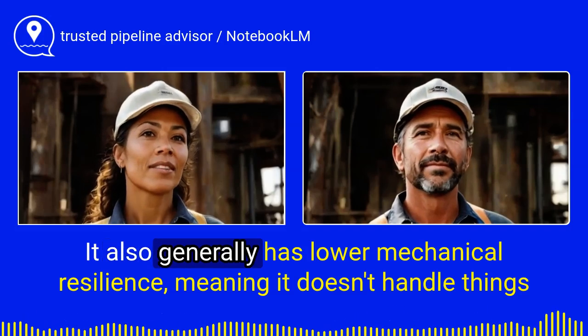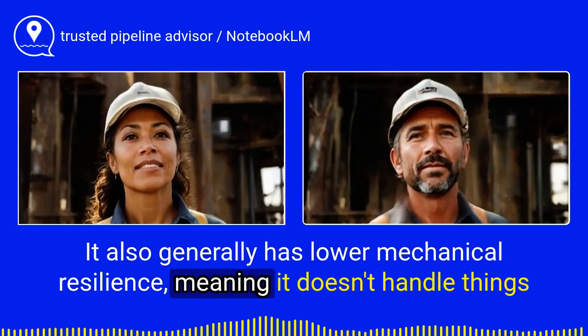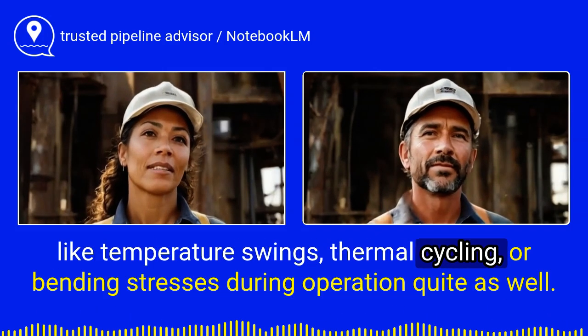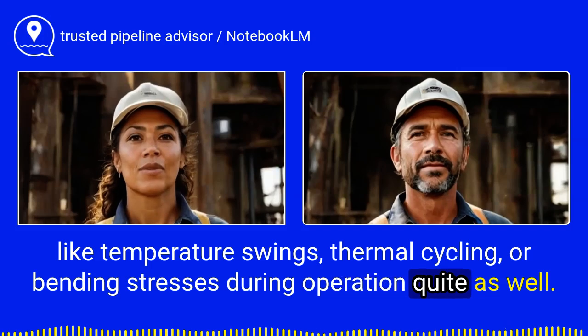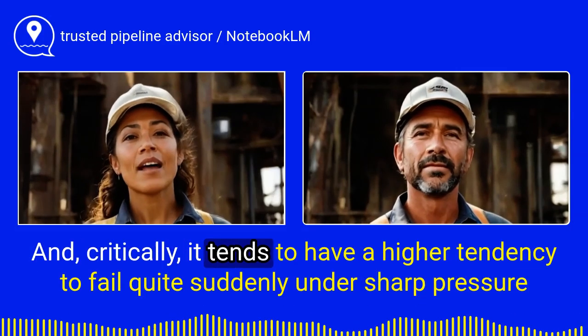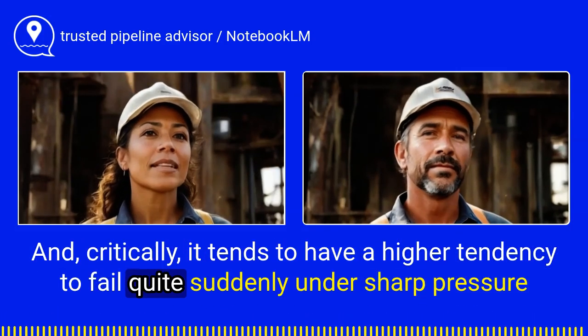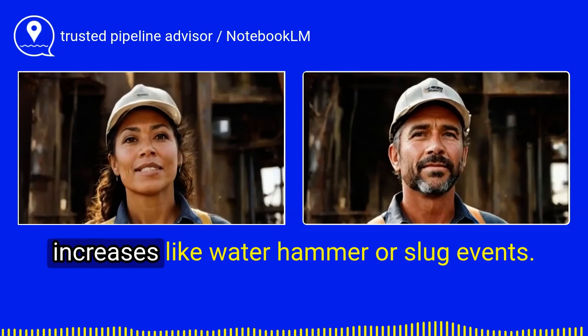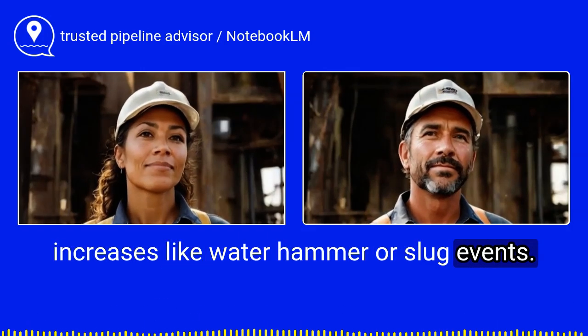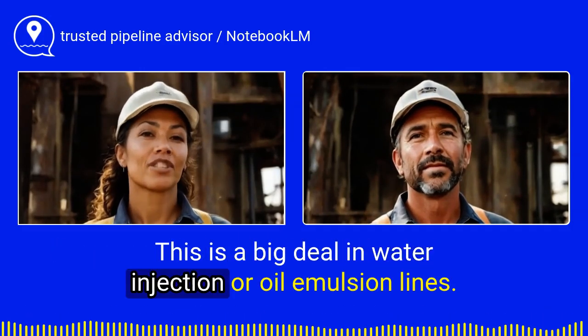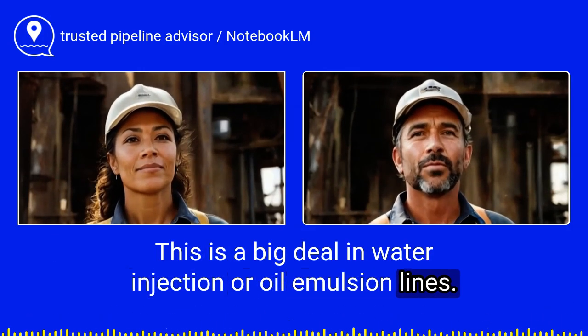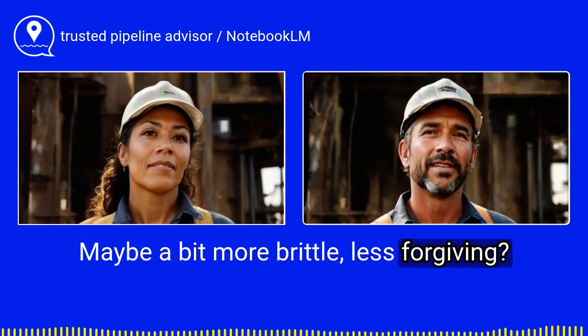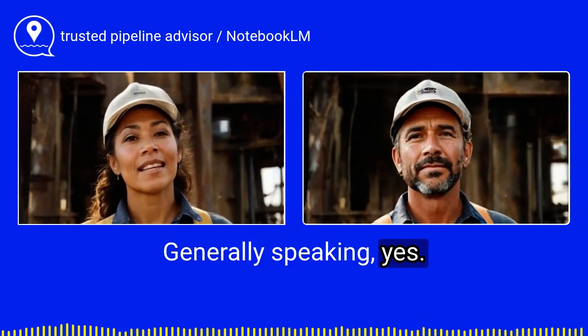It also generally has lower mechanical resilience, meaning it doesn't handle things like temperature swings, thermal cycling, or bending stresses during operation quite as well. And critically, it tends to have a higher tendency to fail quite suddenly under sharp pressure increases, like water hammer or slug events. This is a big deal in water injection or oil emulsion lines. So maybe a bit more brittle, less forgiving? Generally speaking, yes, less ductile.